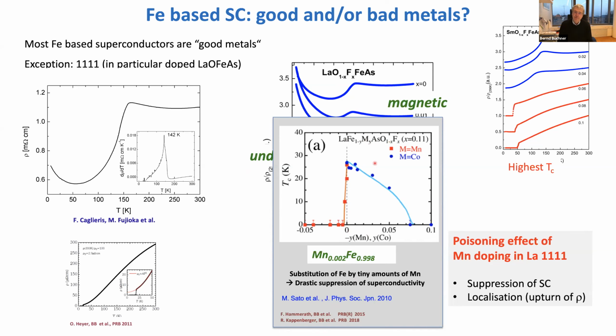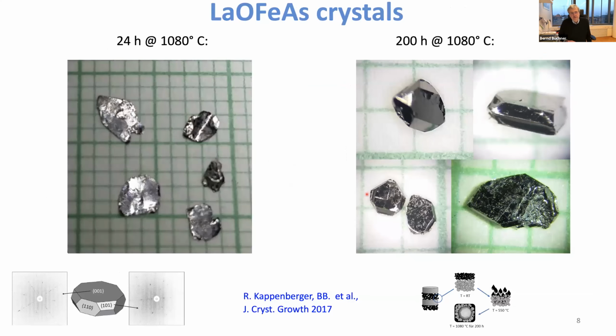And this figure is also important because later on I will show you cobalt doped compounds, and this tells you already that this doping has a strong impact on the properties of these systems. Okay, so that's background. So the big step which we made in crystal growth was done a couple of years ago. It's a very unusual procedure, so-called solid state crystal growth procedure, which allows to grow pretty nice, well-faceted single crystals, three-dimensional single crystals. So that was first done on 1111 type crystals, so on the parent compound of these compounds, and it's still an ongoing procedure.